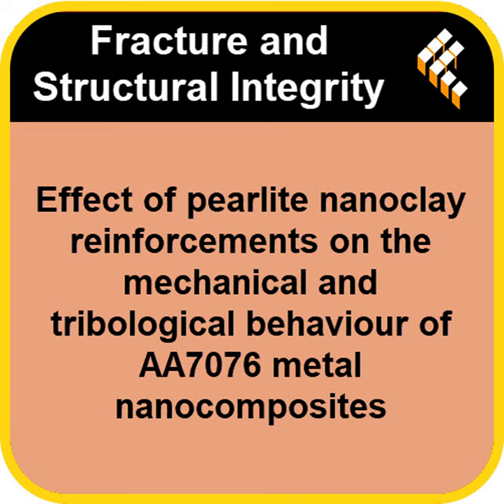So wrapping this up, what's the ultimate conclusion you draw from this deep dive? I think the conclusion is pretty clear. This research has strongly validated perlite nanoclay as a seriously efficient, potentially very cost-effective, and sustainable high-performance reinforcement for aluminum alloys. Specifically, the AA7076 composite with just 1.5 wt% of this stuff offers genuinely superior mechanical properties at 32% higher hardness, 38% higher strength, plus excellent wear resistance. It makes it look immediately viable, or at least highly promising, for lightweight structural uses across automotive, aerospace, maybe even marine industries. A genuine supercharger for alloys, sourced from something natural and cheap. It really is a great, low-cost, high-performance story.